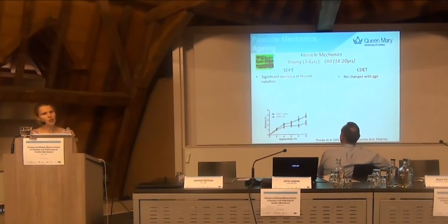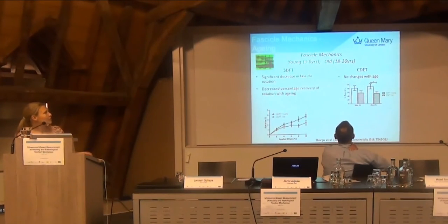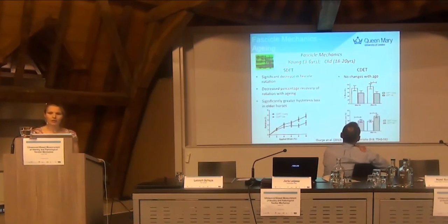But when we started to look at the energy stores, remember these graphs we said applied strain against whatever we're interested in. Here was that rotation we saw in our young samples. Significant reduction in that with age, in the old energy storing tendons. Here, if we look at recovery, significant reduction in recovery in the energy storing tendons with age. Yeah, hysteresis loss, of course, therefore increases as well.